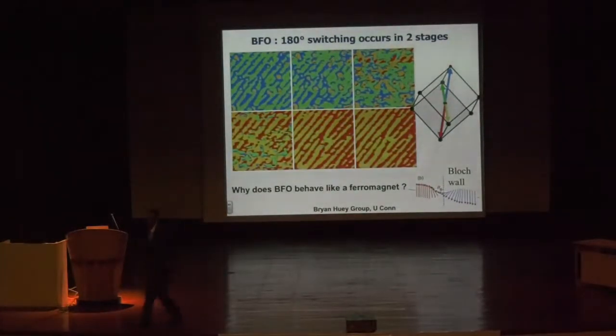In contrast, the conventional wisdom for a ferroelectric was that the dipole moment would continuously change. The dipole moment was never thought to be a fundamental quantity. It's a mutable quantity. So it was big on one side, slowly decreased, and then flipped over to the other side. Instead, bismuth ferrite was telling us that it didn't do that. It actually rotated this way and did a second switch. And so we're still saying, that is very strange, and we don't understand it, which is why I put a question mark. Why does bismuth ferrite behave like a ferromagnet?